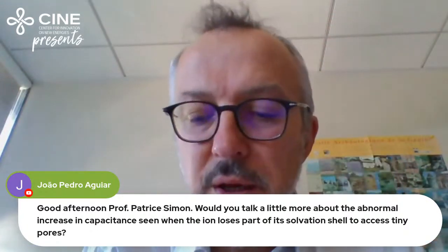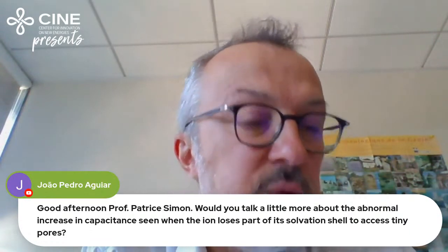I would like to talk a little bit more about the abnormal increase in the capacitance when the ion loses part of its solvent. I did not spend a lot of time on that because it's all resolved now. We called it abnormal 15 years ago, because when we found it, it was difficult to explain. But since then, a lot of people have explained it, even by modeling. When you have an ion with solvent molecules, the approaching distance is given, but when you remove part of the solvation shell, you can get closer to the surface, you decrease the approaching distance, and then you increase the capacitance.